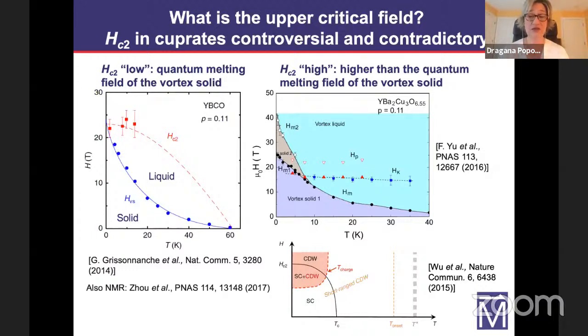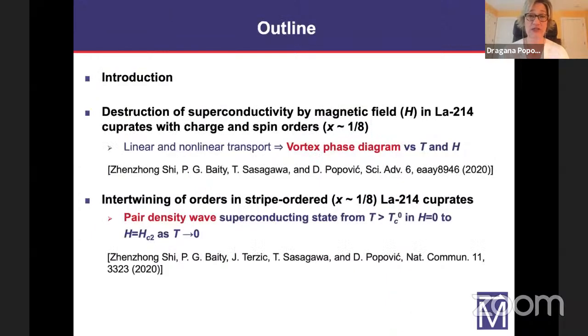So in order to actually address the question that we are interested in, we first need to resolve this issue. So after this introduction, the first part of the remainder of my talk will focus on trying to understand how a magnetic field destroys the superconductivity, and we want to map out the vortex phase diagram as a function of temperature and field. For that purpose, we also use nonlinear transport measurements in addition to linear transport, because nonlinear transport is a direct probe of vortex matter. And then in the rest of the talk, I will focus on our evidence for the presence of the pair density wave in these materials.